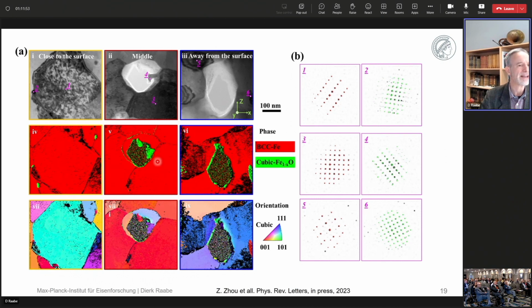You see here the red contrast showing where the material was fully reduced into body-centered cubic iron. All good and fine. But then you can see the pores in the center, which contained so much water building up so high pressure, as you can calculate with the phase field model or analytically, that you obtained local reoxidation. That means the volume around that pore, due to the captured water which could not escape, which could not percolate outbound, you have reoxidation of this inner perimeter around the pore.